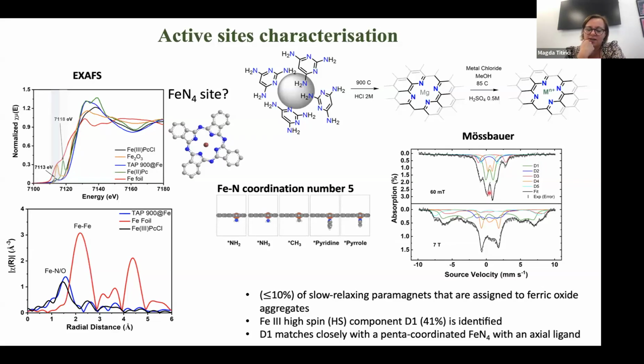So we learned that mostly we have iron(III), about 41%, and that this iron(III) is actually coordinated in a penta-coordinated manner, which means that you have these nitrogens, but you have another axial ligand here. And this was also confirmed by X-ray absorption spectroscopy. So here you need to go to a synchrotron and you do some standards. So you do iron foil, where you see iron-iron bonds. Then you can do an iron phthalocyanine, which has the single iron site, and you do your catalyst.